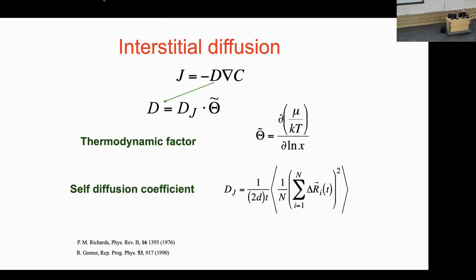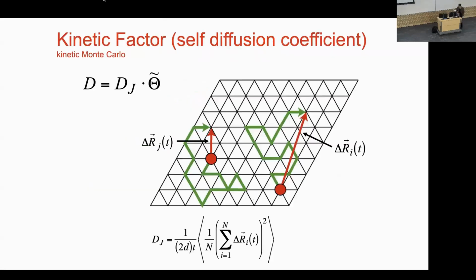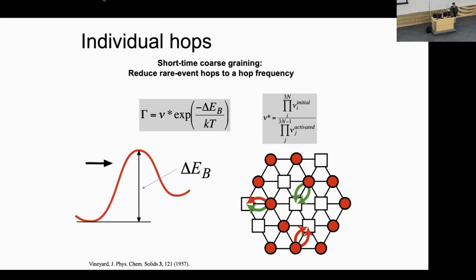And this one is a quantity that you can calculate with kinetic Monte Carlo. And so the way that works is you have a bunch of sodium atoms or lithium ions in a crystal, let's say on a triangular lattice. And with kinetic Monte Carlo, you can sample different trajectories. You take the endpoints after a certain time. These delta R's are the endpoints of those trajectories. You sum them up, you square it, you divide by the number of lithium ions, you divide by the time of the simulation, and that gives you a measure of the diffusion coefficient. And what you're really keeping track of is the geometric center of mass of these atoms that are in equilibrium, but they're always fluctuating and diffusing around. And that gives you this thing. And so you can calculate the diffusion coefficient.